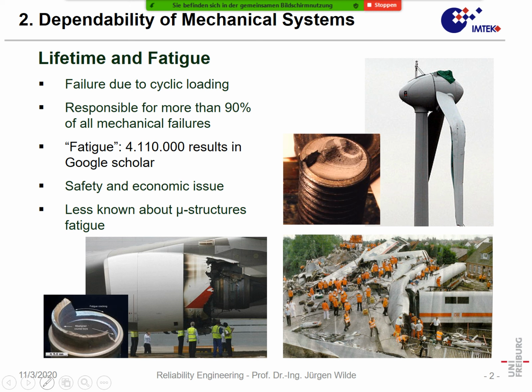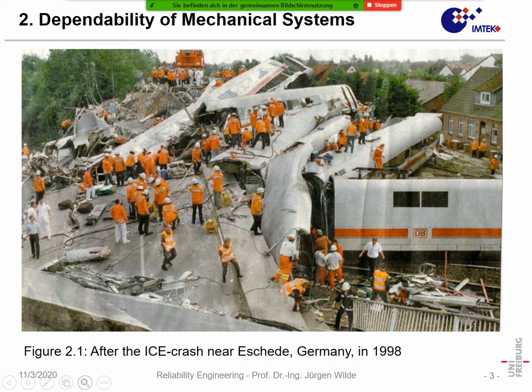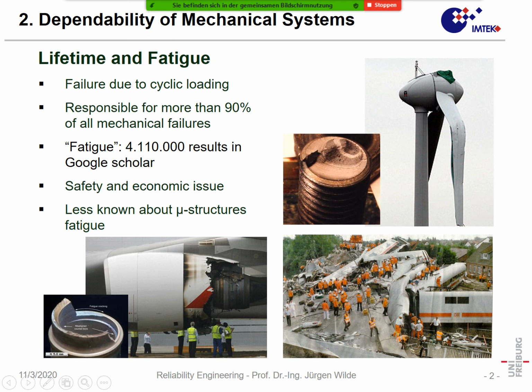Just to give you some examples where single components failed. For instance, on top we have typical fatigue failures. In the lower left case, a turbine blew up in an aircraft. That can be very dangerous, because when the turbine blades break, they can fly through crucial parts of the aircraft. For instance, they might sever the control which gives control over the aileron and so on. And in that way, just by a crash of such an engine, the complete aircraft could be lost.